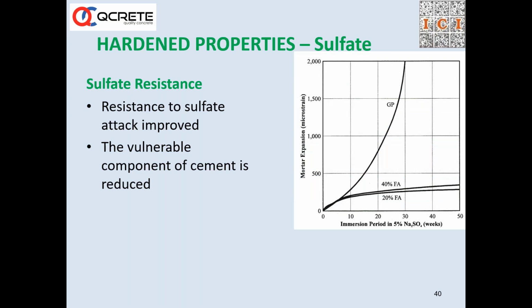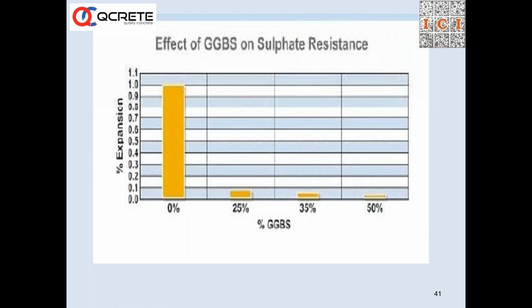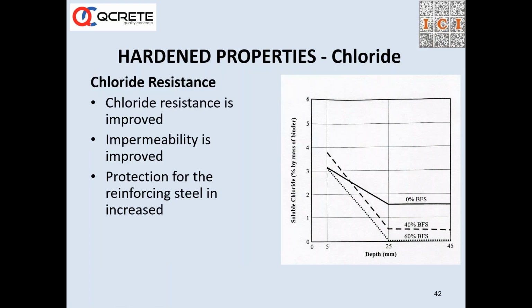So sulfate resistance is another aspect which is significantly improved by addition of pozzolanic materials. We can see here fly ash addition of 40 to 20% against the general purpose, that is normal cement, where it is almost going parallel to the x-axis, means expansion is less. Expansion is maximum when you're talking about the OPC. So resistance to sulfates is enhanced, resistance to chlorides is enhanced. We can see here when you're adding 60% of GGBS, there is no chlorides penetrated at a depth of 25 mm in a concrete system.